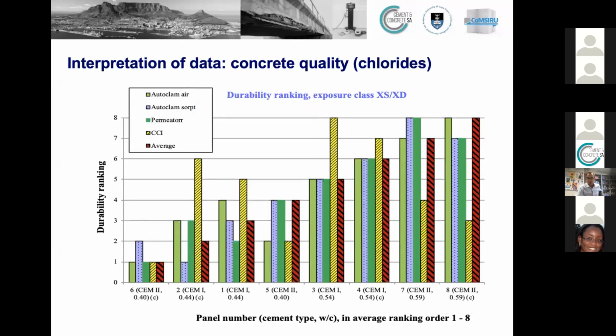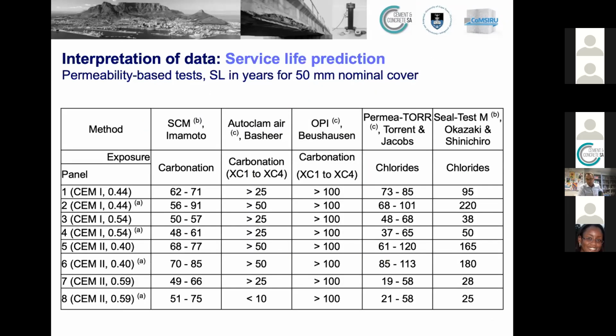Looking at exposure conditions related to chloride ingress, we had a very similar picture where, on average, the test methods tended to agree. So once again, I would say thumbs up, we are on the right track. However, then we also compared the service life prediction. Now we use the test values obtained to predict or to quantify the service life of our concrete structures. And there we have totally different values for the different concretes. For example, for concrete A, looking at the first one, the values would range between 25 years to more than 100 years. So there was no consensus at all.